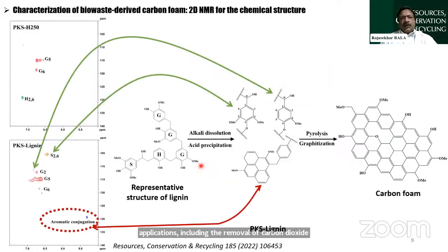Let me give you some insights as to what kind of chemical transformation pathway is actually happening in the process of depolymerization of the biomacromolecule to produce lignin and eventually carbon foam. Now you can see over here, you have all these chemical compounds, which I don't want to discuss in detail. These are all important components of lignin. Once you do the pyrolysis, all these aromatic compounds will form a macromolecule, as you can see over here. This is a huge macromolecule, and through graphitization, that will produce carbon foam eventually, which is rigid. We also did a 2D NMR characterization, which I don't want to go into details about at the moment.